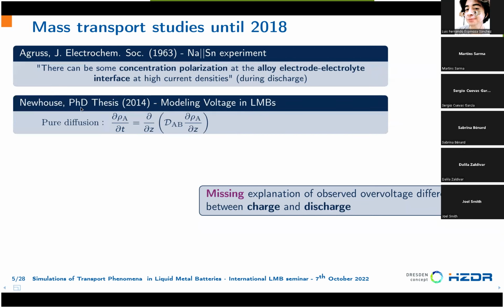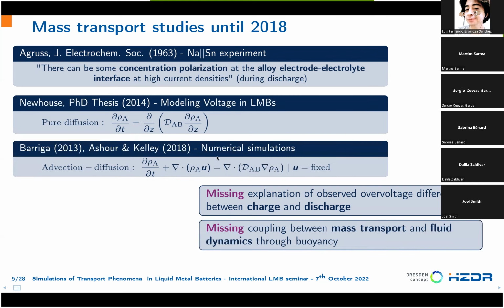This means that there is some difference between charge and discharge, but no one was able to explain it. More recently, in the PhD thesis of Newhouse, a diffusion model was used to study the voltage evolution in the liquid metal batteries. And later, Barriga, Ashour and Kelley used an advection diffusion model to study the transport of the concentration inside the positive electrode. This model used a fixed velocity, and therefore it is missing the coupling that there is between mass transport and fluid dynamics, and this coupling is thanks to buoyancy, as we will discuss later.